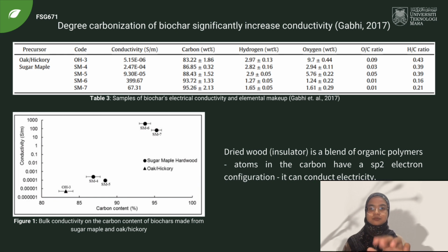It is clear that the degree of carbonization of biochar has significant impacts on its conductivity. An additional few percent more carbon can significantly increase conductivity. This conclusion makes sense since dry wood is an insulator, being a blend of organic polymers, yet if the atoms in the carbon have an sp2 electron configuration as they do in graphite and graphene, then carbon can conduct electricity.